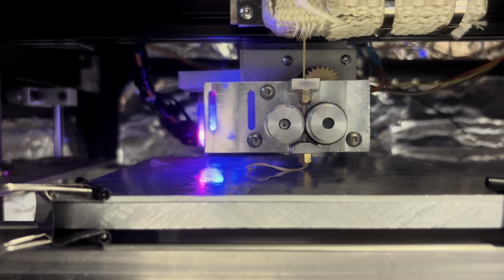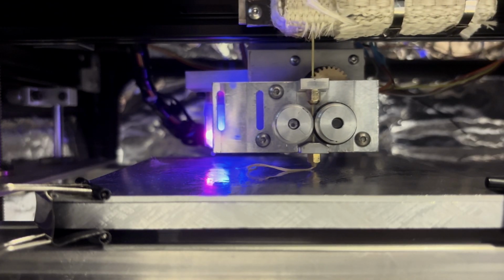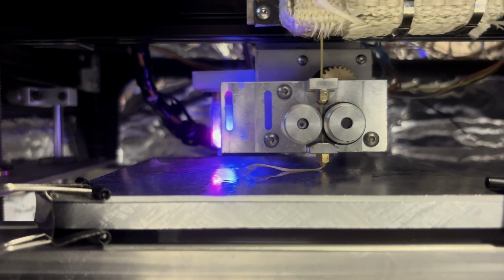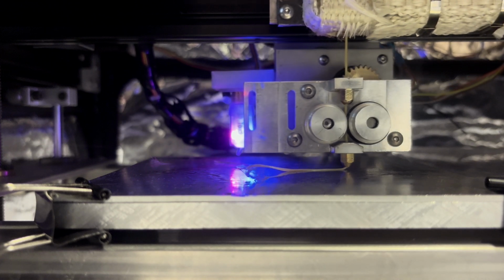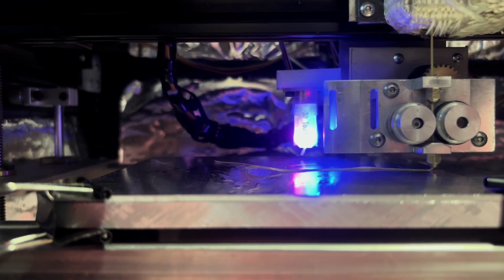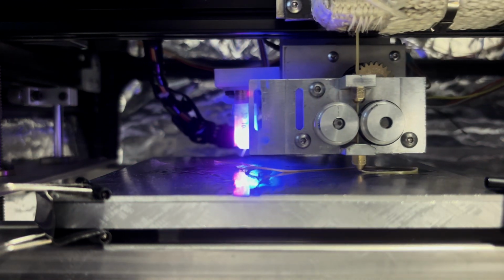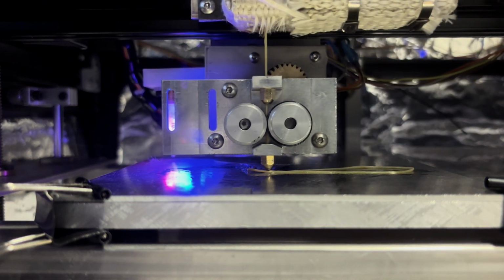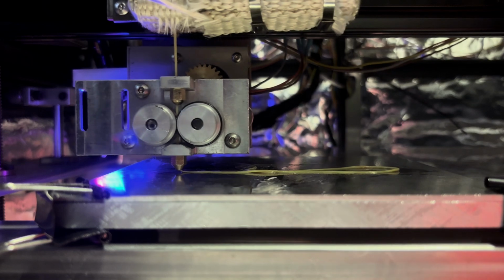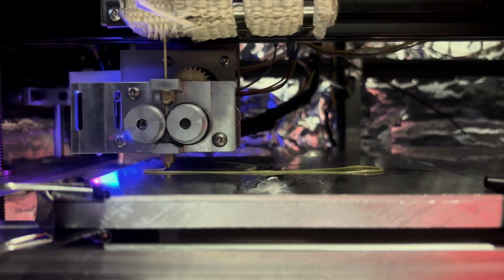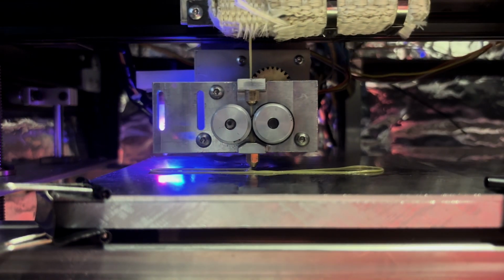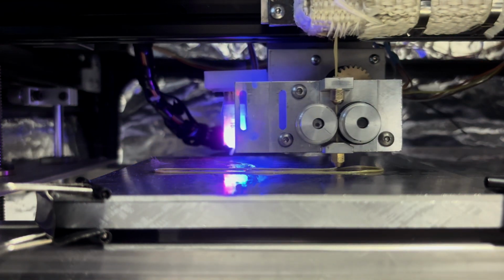Right now you can see a video of how printing went before any modifications were made. As you can see, the print starts off promising, but once it reaches any change in geometry, it begins to lose its shape and drag along the plate. The coding for the extruder was set at a singular invariable speed, meaning that the extruder was unable to keep up with the print and would thus drag it along.